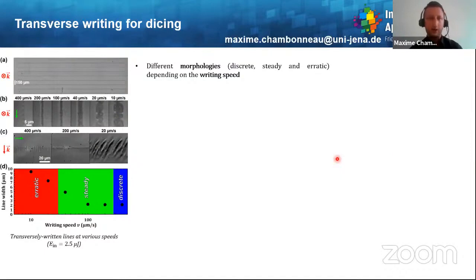Okay, so let's try to push again a little bit the limits. And what happens when one moves the sample with respect to the incoming light? So here are the results shown on the left. Here I show you that it is possible to do some transverse writing inside silicon.